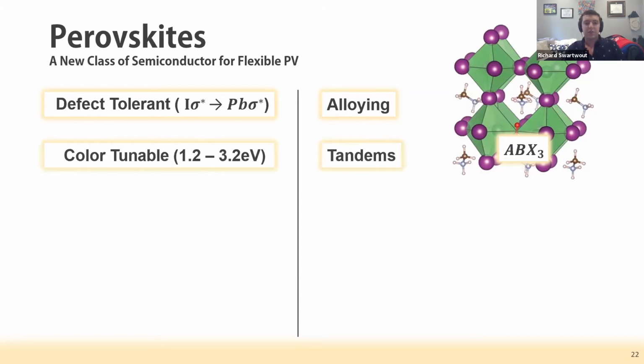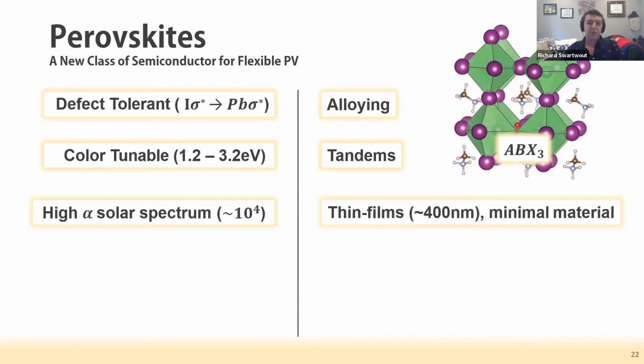Because of the alloying, they're color tunable, so we can go all the way through the near IR into the UV. I'm not going to talk about it today, but this brings up the idea of tandems. They have a very high absorption spectrum because of their direct bandgap nature. The films I showed previously were about 400 nanometers thick, and they were optically opaque. So that does really mean that we're not using a lot of materials. This really means it can be economical.